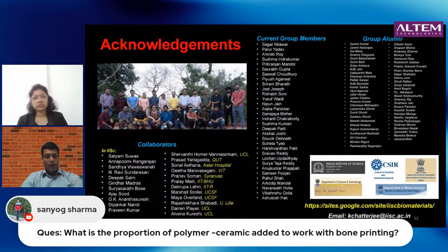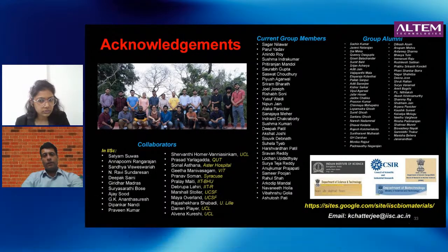Right. So let me put it this way. If you're talking about the work we did with ceramics, there we were just modifying the surface. We weren't really mixing the ceramic with the polymer, which you could do also. That certainly is a possibility. But what we did was take polymers that are used as biomaterials. In this particular case, we're looking at polylactic acid, and then we modified the surface. The amount of ceramic is very, very little actually, because it's just a very thin coating of nanomaterials. In fact, it's small enough that it's difficult for us to actually quantify it,